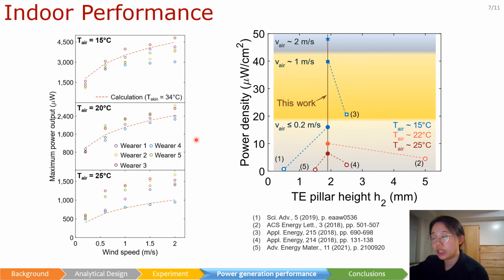Since the skin temperature varies from person to person, the power generation performance could change with different wearers. In this slide, we show the performance testing results with more volunteer wearers, including female and male wearers, and comparison with our analytical prediction, shown in the dash curves. The skin temperature in the model is set to be 34 degrees C, which is the average hot side temperature we measured. Good agreement is achieved between our analytical model and measurements. Our device measured the maximum output power densities are the highest reported values for flexible thermoelectric generators on human skin without using the external heat sink in similar thermal environments.